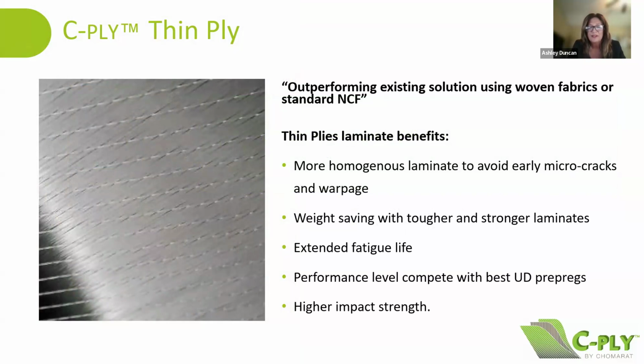Well, compared with traditional woven fabrics or conventional NCF architectures, thin ply laminates offer several important performance advantages. These include a more homogeneous laminate structure, which helps reduce earlier microcracking and warpage, improves strength and toughness while simultaneously reducing weight, extended fatigue life, mechanical performance approaching unidirectional prepreg systems, and improved impact strength.